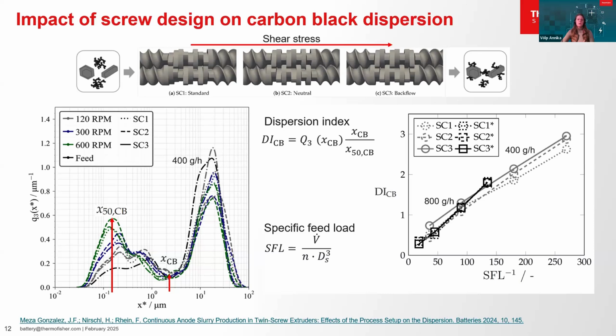The specific feed load is the volumetric throughput divided by the screw speed and the screw diameter cubed. The right graph shows a good correlation of the dispersion index with the reciprocal feed load and a decrease in carbon black deagglomeration with increasing screw speed. Therefore, the specific feed load provides a good basis for scaling anode slurry mixing, assuring consistent carbon black deagglomeration. On the next slide, we see the screw speed impact on carbon black deagglomeration in SEM images.